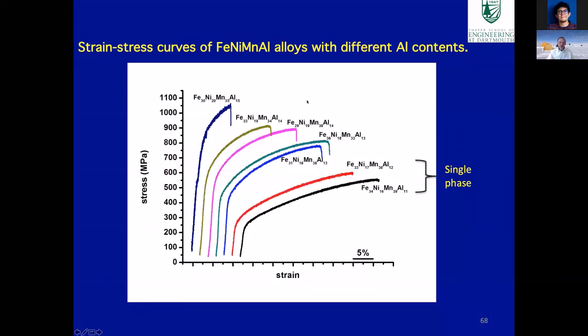And so we looked at mechanical properties as we change the aluminum content. So this is the alloy we talked about before with 15 aluminum, and these are low amounts of aluminum. Also, some of the manganese has changed as well. And as we lower the aluminum content in the alloy, these are still two-phase, the yield strength goes down, but the ductility increases. These two are over here where we've decreased the aluminum down to 12% or 11%. And in these cases, actually, yield strength is quite low, but lots of ductility. But these are single-phase materials.